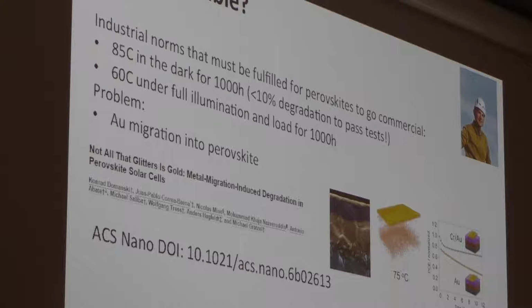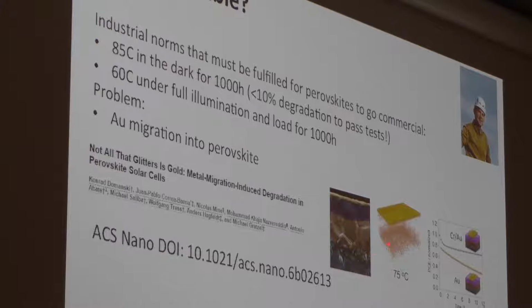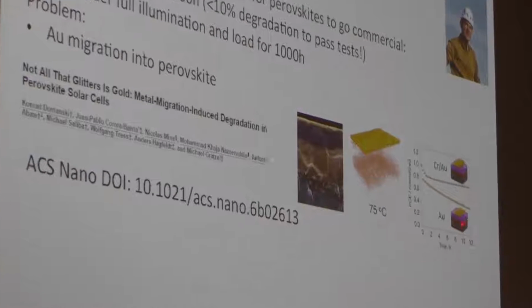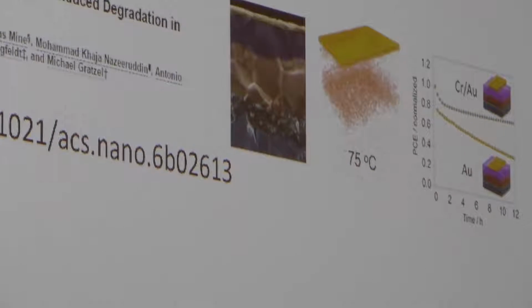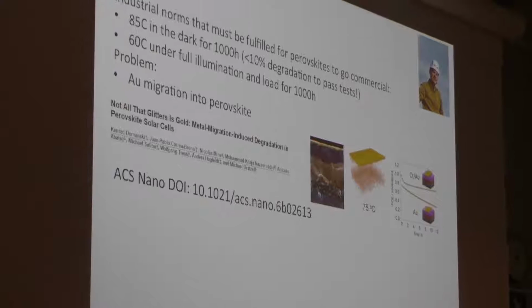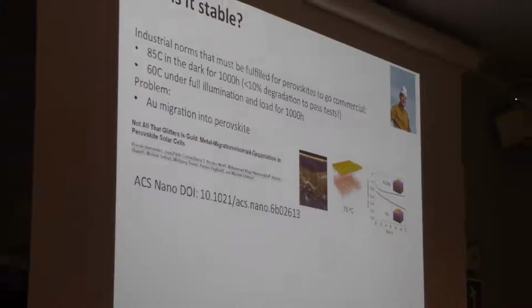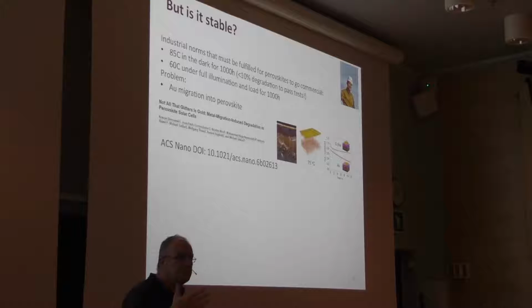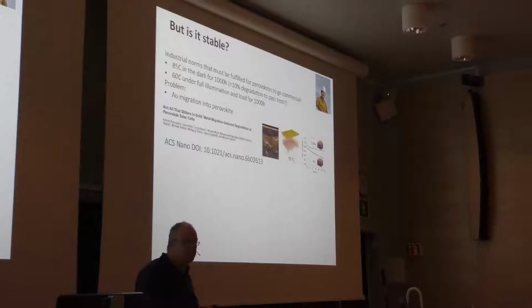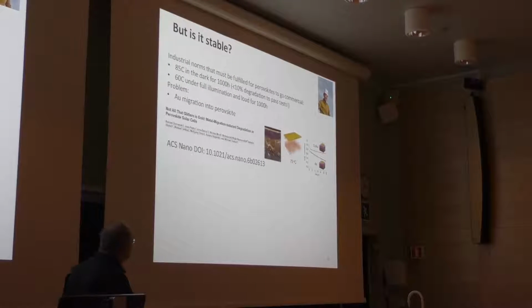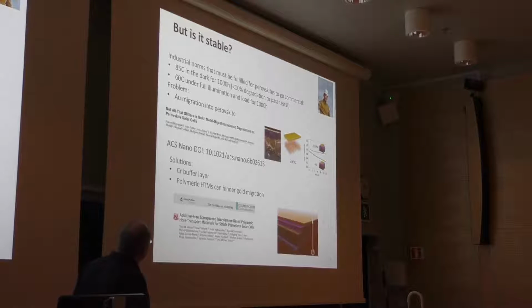But so we did a SIMS study and to see what elements do we have in the structure. Surprising to us at least was that we had a lot of, or not a lot, but we had gold in the perovskite structure. So gold diffuses through the Spiro into the perovskite, and that's the cause of degradation. It had nothing to do, we think, not much at least, with the perovskite. It is the gold Spiro contact at high temperature which is the problem. So that was very important for us, because then we could start to think what can we do about it.